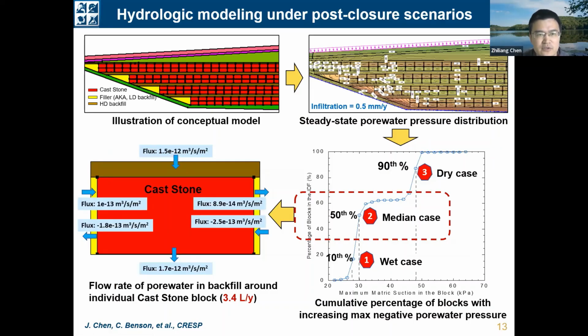So specifically for this post-closure scenario, because of the existence of the cover at the top of this facility, the pore water in the backfill will be spatially redistributed. So that means some blocks may be in wet condition, like these blocks, and some will be in medium condition, and some will be in dry conditions. So the results at the bottom are an example for the median case, and the contaminants released for 3 different cases will all be estimated in this work.